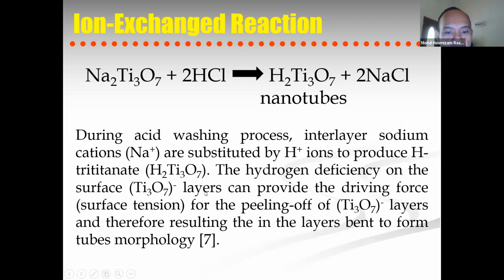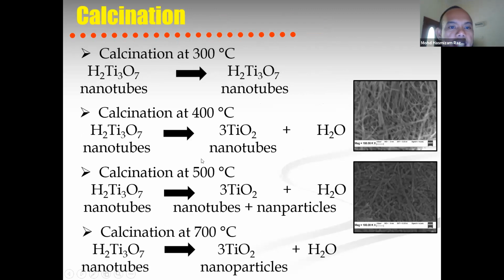The explanation is as follows. The hydrogen deficiency on the surface layer provides the driving force, surface tension, for pulling off the titanate layer, and the resulting layer bends to form nanotube morphology. Then this is the calcination. The hydrogen trititanate nanotubes remain hydrogen titanate nanotubes after calcination at 300 degrees C, so the titanate is thermally stable at 300 degrees C. That is why we have to increase the calcination temperature to 400, 500, and 700 in order to obtain titanium dioxide nanotubes, which is our aim in this experiment.